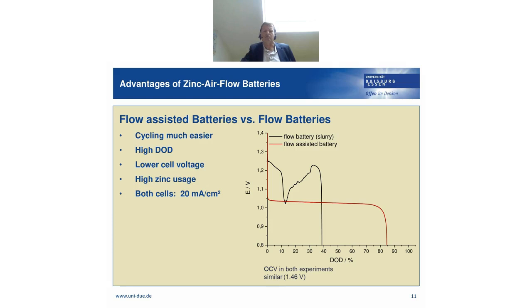We have done some experiments to characterize and to compare these two ways of battery operation. Here the black line is the flow battery, so this has our slurry, and in red we have the flow-assisted battery. For both experiments, we have taken the same current density, 20 milliamps per square centimeter. The slurry cell had a 50 weight % slurry, and for the flow-assisted battery, we had dissolved 0.9 moles per liter of zinc oxide, and then converted it to zinc. So what is obvious here, the flow-assisted battery has quite a high depth of discharge, or DOD abbreviated, of 85%. And the flow battery has a DOD of only 40%.